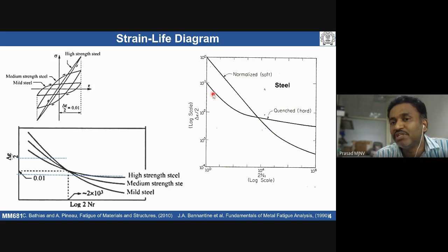It is going to be opposite when you talk about low cycle fatigue. So one has to be cautious while selecting a material for a given application. Upfront, we have to know for the particular component how many cycles it is going to experience, and is there plastic deformation? That means the stress is higher than the yield stress or below the yield stress. Accordingly, you have to select the material. Material selection for low cycle fatigue is different than for high cycle fatigue performance. Is it clear?